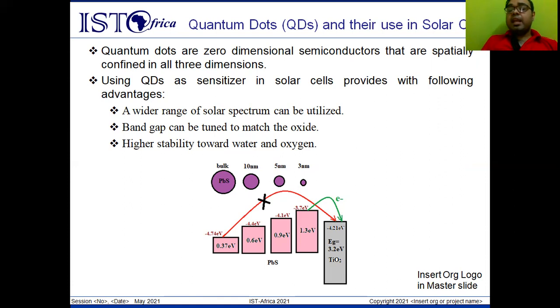Also, the band gap can be tuned to match the oxide. One of the most important properties of quantum dots is that if we go on reducing the size of the quantum dot, the band gap increases. So we can tune the band gap of the sensitizing material, that is the quantum dot, to match that of the depositing oxide. As we can see in this figure, by reducing the size of the lead sulfide quantum dot, the band gap increases. And we know electron jump is easier from higher energy to lower energy compared to lower energy to higher.